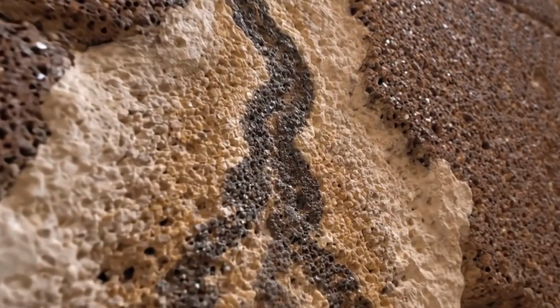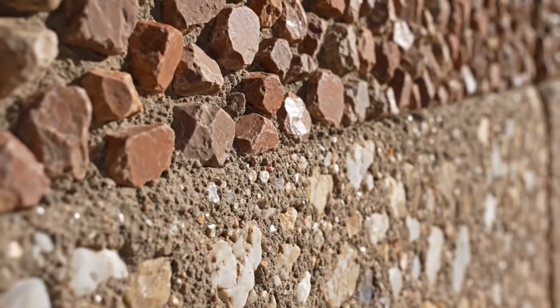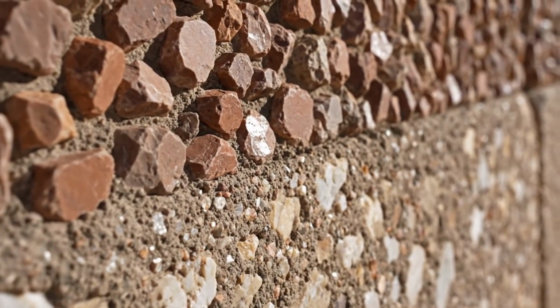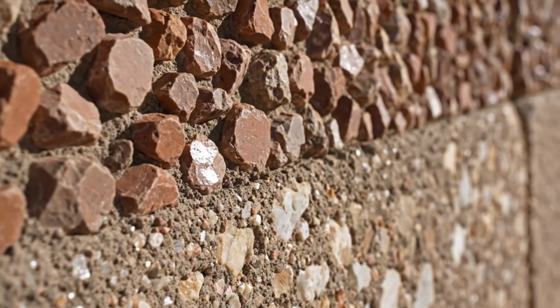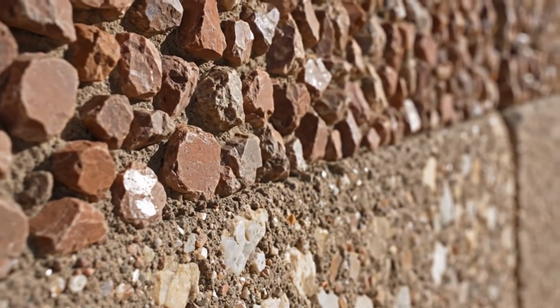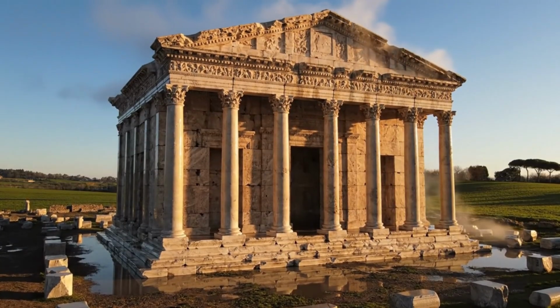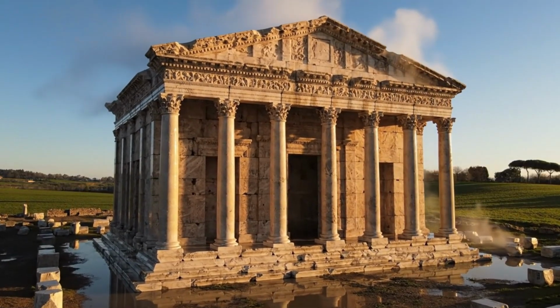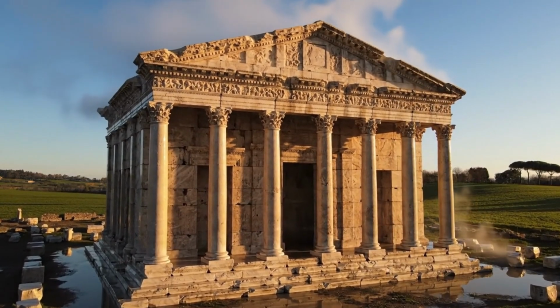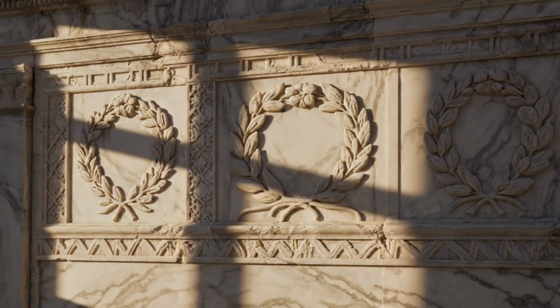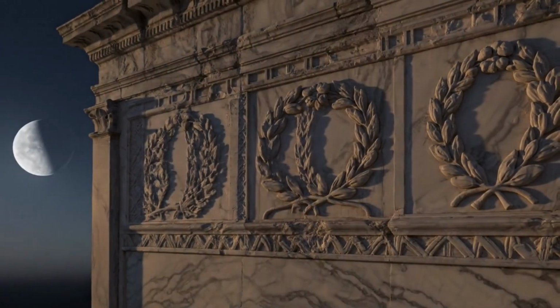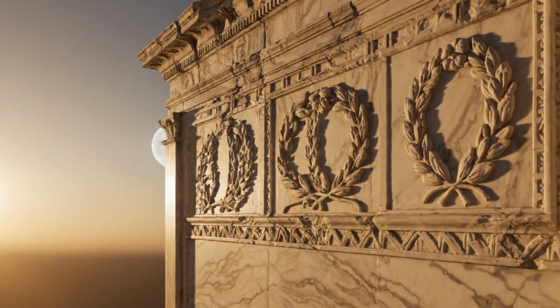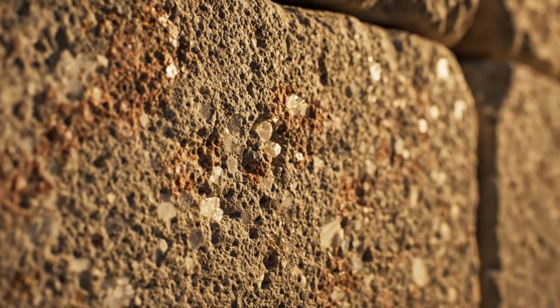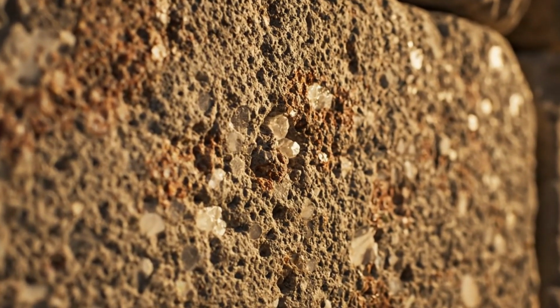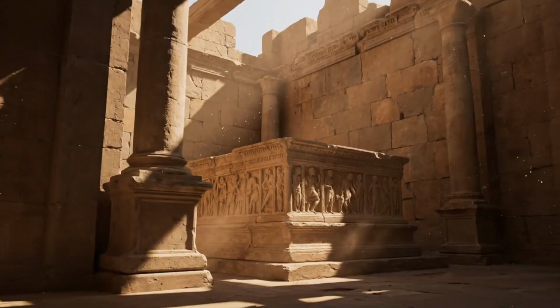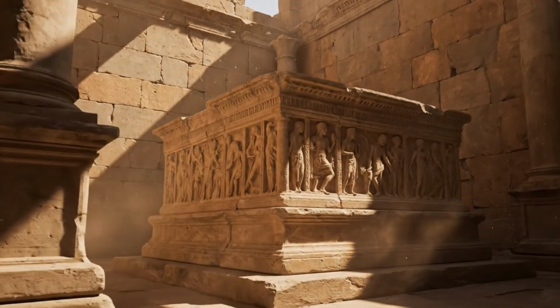In the case of the tomb, the potassium-rich environment fostered a distinct evolution of the binding phase, reinforcing the interface between aggregates and mortar. These interfacial zones are critical to the durability of any concrete. They are the regions where coarse fragments meet the binding matrix, and they often represent the weakest link in modern materials. In the tomb, however, the long-term remodeling appears to have strengthened these zones, rather than weakened them. The microstructure did not simply endure the passage of centuries, it adapted within it.